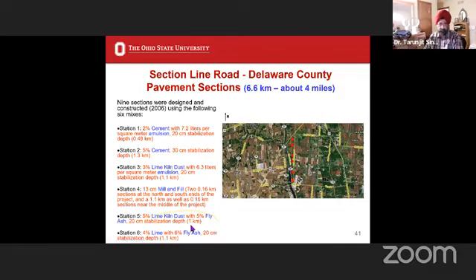Station 5, for 1 kilometer, was 5% lime kiln dust with 5% fly ash. All of these were designed with a depth of stabilization depending on the traffic. And this is quarry traffic. So this road up here has a quarry by a strand road. So this has heavy truck loading coming on it.